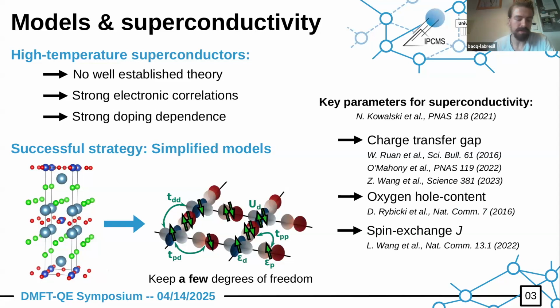And I think that one work that summarizes all this progress as far as superconductivity in cuprates is concerned is this work by Kowalski and collaborators, which was done in the group of André-Marie and David in Sherbrooke, where they could identify, if I were to summarize, 3 key parameters for superconductivity, which relate to all these experimental works cited here in the slide. So these parameters would be the charge transfer gap, the oxygen hole content, and the spin exchange J.